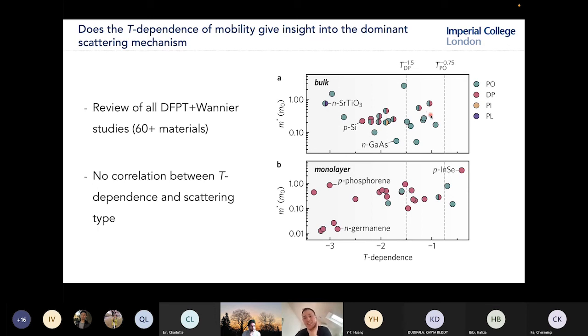The first is that if we pick a particular mechanism, for example, polar optical phonon scattering, so here I'm just looking at these teal points, you can see that the temperature dependence really varies across a very large range. It goes from effectively minus 0.5 all the way to minus 3 just for this one mechanism.